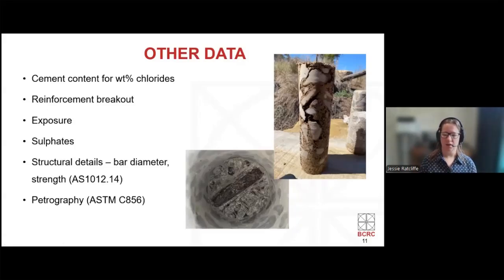In addition to our key condition assessment data, there are a few other factors we can measure while we're out there, including our cement content. If we're finding our remaining life based on chlorides, this is important because we are looking for 0.4% chlorides per weight of cement, not per weight of concrete. So we need to know that cement content.